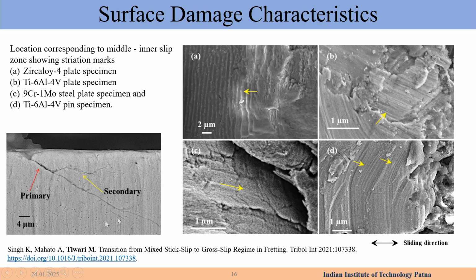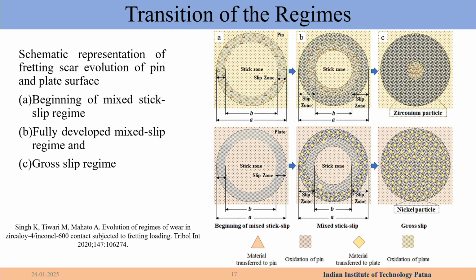By the way, there are other materials also which have been tested in this, just because Zircaloy with Inconel is partially compatible. 9Cr1Mo steel with titanium 6Al4V is compatible, right? So we wanted to see what is the difference between partially compatible and compatible pairs of material. If you take all the pictures we've seen, the slip zone here increases and the stick zone is going down, and also you see that the zirconium particles are being collected at the center, and the nickel particles being formed. So the one is the pin and this is the plate.